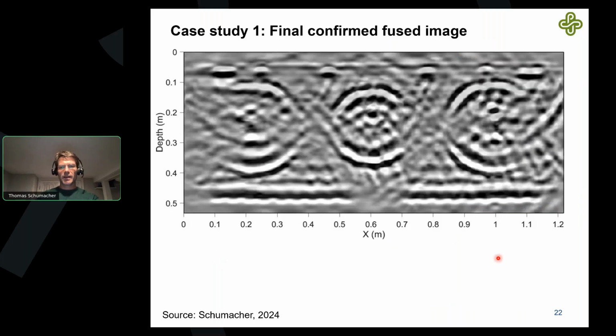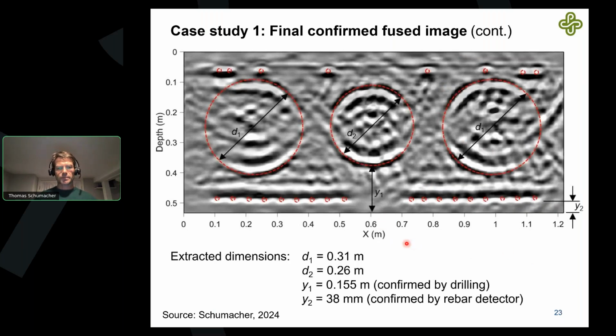157 millimeters. So now what we can do, we can take this, we can go in and we can determine all these measurements. So we know we can determine the size of the void. That helps us determine the self-weight of the structure exactly, which is an important part in the structural evaluation. We can measure, based on the reflectors, we can measure the cover. In the image, we got about 38 millimeters. The rebar detector said 36, so we're very close there. The distance from the bottom to the middle void in the image told us it's about 155 millimeters. We measured 157, so we are within a couple of millimeters here.